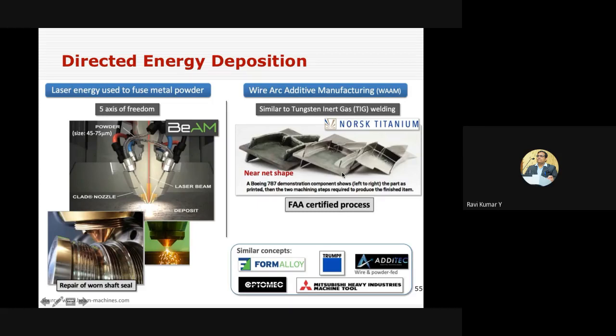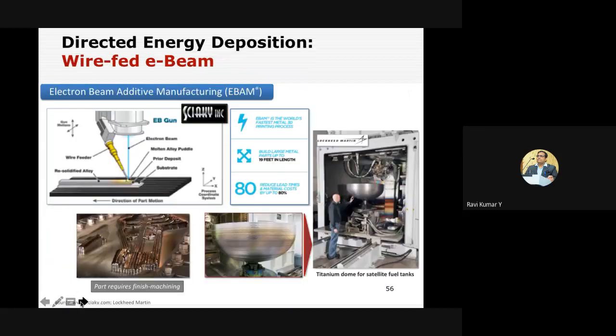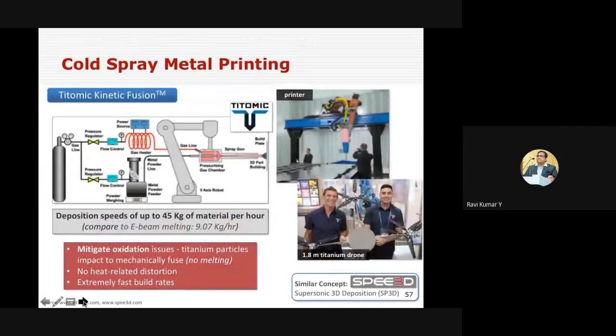Sciaky, which we discussed through that video, and then cold metal spray printing, that's quite amazing. It can be even 45 kg of material per hour, whereas the existing conventional rate is maybe around 9 kg per hour, but it can be 45 kg per hour. I am talking about per hour, not per day. So you have such cold spray metal printing, and huge developments are happening.